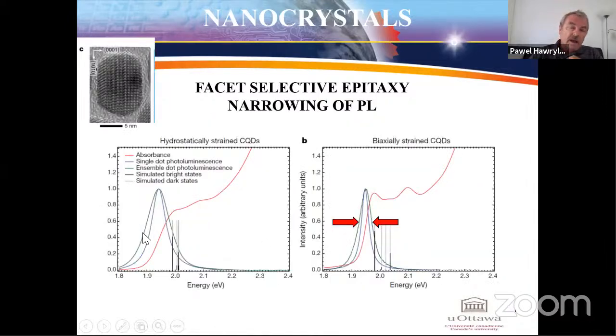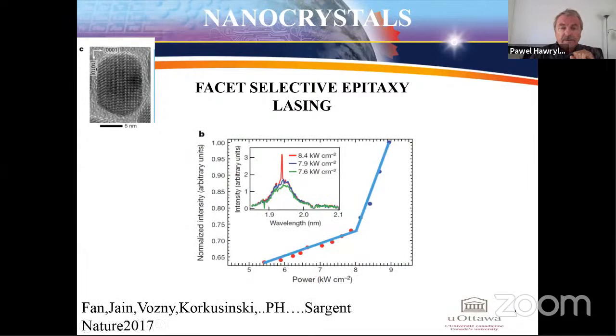And here is an experimental result of absorbance and photoluminescence. So this is a photoluminescence peak, and before this facet selective epitaxy, the peak was very broad due to this band of states at the top of the valence band, but the biaxially strained quantum dot due to this facet selective epitaxy resulted in a narrow recombination spectrum because of this removal of degeneracy of the band. And so this is a final result.